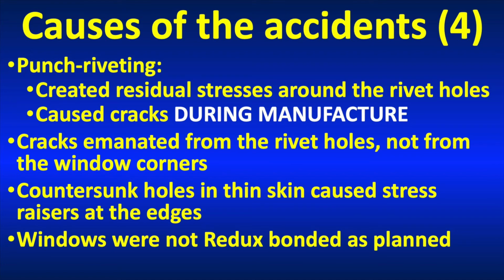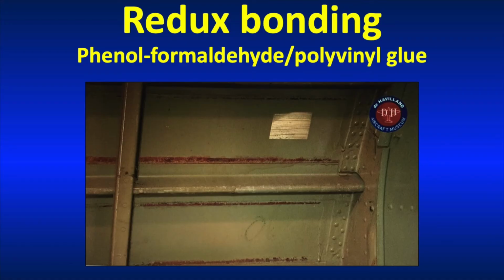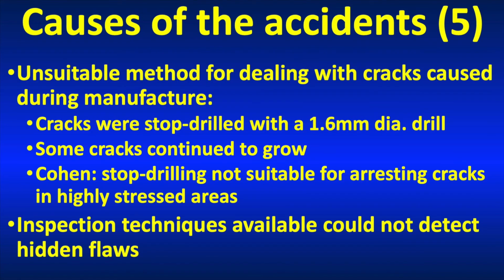But to me, if I were an aeronautical engineer working on the Comet, and I see cracks being caused by riveting, I'm going to say, well, gee, this is fairly serious stuff we're dealing with here. Thin skins and countersunk holes don't really go too well. So let's have a look at this Redux bonding. This is a section of Comet fuselage with the stringer Redux bonded. And had they used Redux bonding around the cutouts, the windows, etc., I don't think these accidents would have occurred, or certainly not when they did, because gluing them in place means that you have a very even distribution of stress rather than the stress concentrations that they ended up with. But in the end, they didn't do it, and history is history.